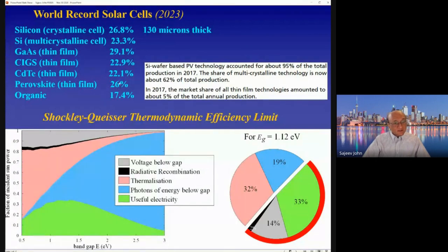They have reached an efficiency of 26%, and organic or polymer solar cells with efficiencies of 17%. The latter two have received a lot of attention, but they suffer from stability issues, and the perovskites, as you may know, involve some hazardous materials. So despite all this laboratory activity, the industry is still dominated by silicon, and about 95% of the total production,